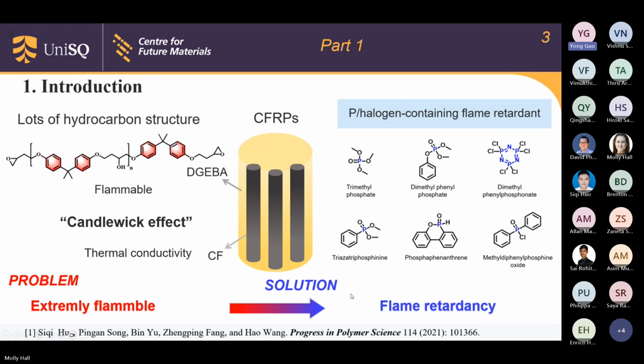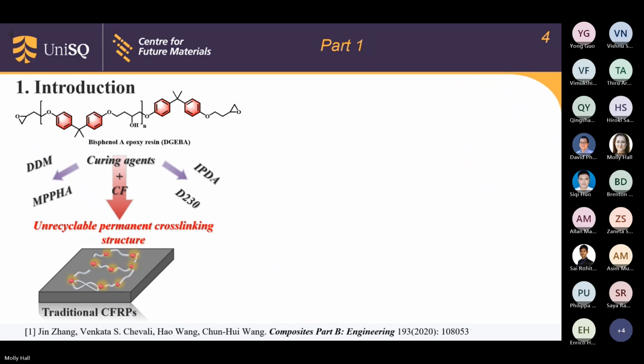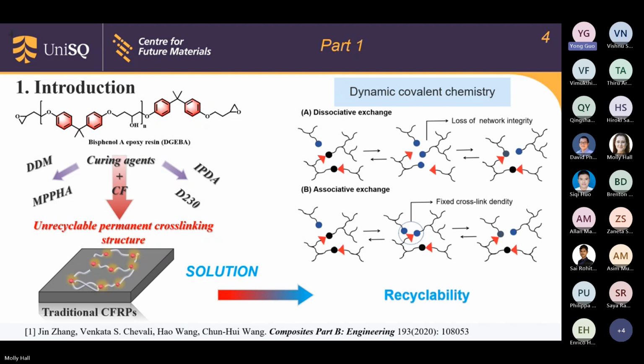Recently, research has focused on using phosphorus and halogen containing flame retardants to insert into the epoxy resin to achieve flame retardancy. As we mentioned, the CFRPs consist of DGEBA and the CF, and the DGEBA is paired with curing agents such as IPDA, D230, DDM, and MPPHA, and with the CF to achieve CFRPs. However, because of the unrecyclable permanent cross-linking structure of the epoxy resin, the traditional CFRPs are unrecyclable. So what can we do?